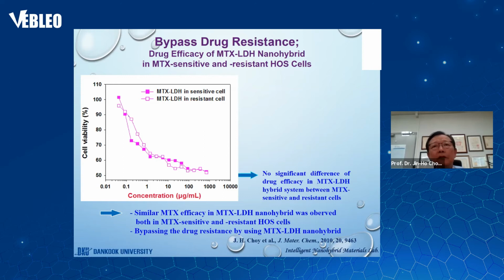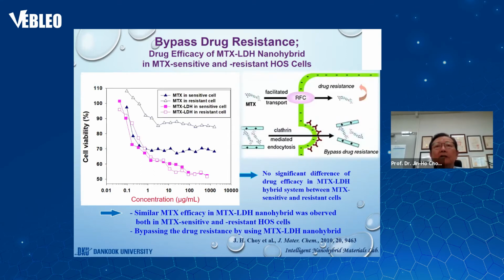Our previous reports demonstrated that the LDH nanocarriers are internalized into host cells via clathrin-mediated endocytosis. The fact that the MTX-LDH takes the same entry as the LDH nanocarrier suggests that the MTX intercalatively encapsulated in the LDH lattice can completely modulate ligand-receptor interaction. It is therefore concluded that the clathrin-mediated endocytic pathway of MTX-LDH is responsible for an enhanced cellular internalization of MTX, allowing the drug resistance to be bypassed.